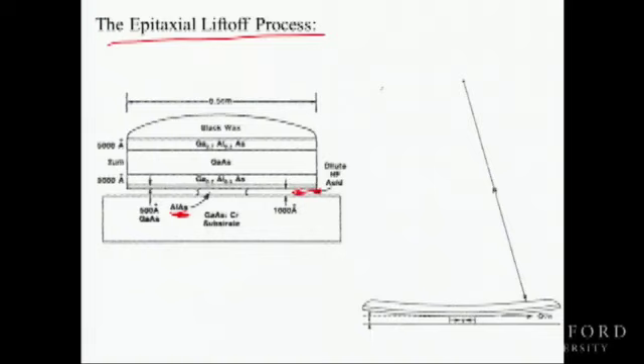So at 40% aluminum, say it this way: at 39% aluminum, it is not attacked by the acid, and at 41% aluminum, it is attacked in the alloy. By yes and no attack, I mean there's eight orders of magnitude in selectivity over a very narrow percentage range of composition. So what this means is you can come in very large distances and just float off these epi layers, and then you can reuse the substrate. The beauty of this is you only pay for the semiconductor you use.